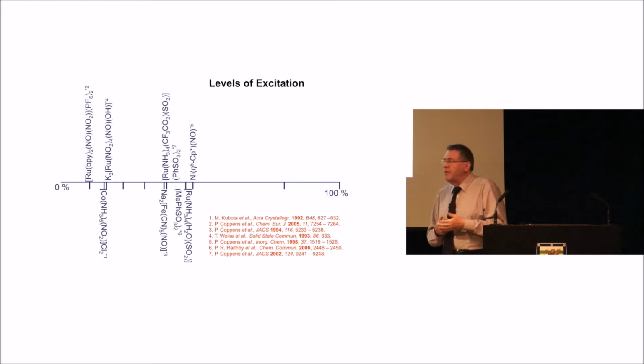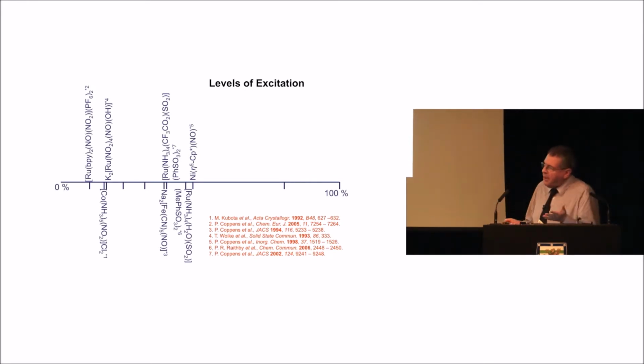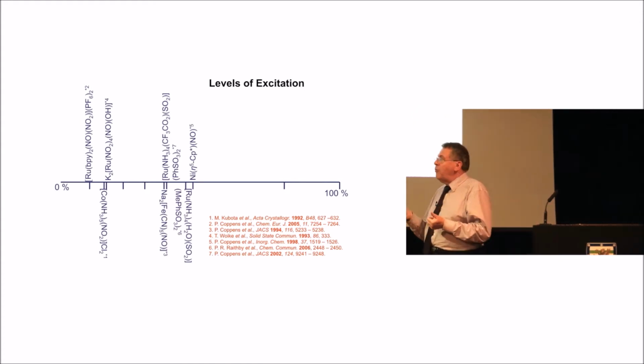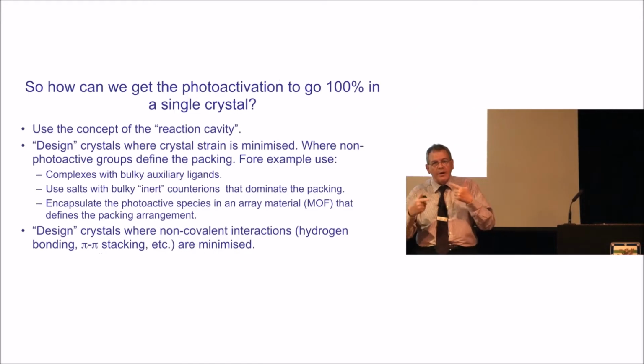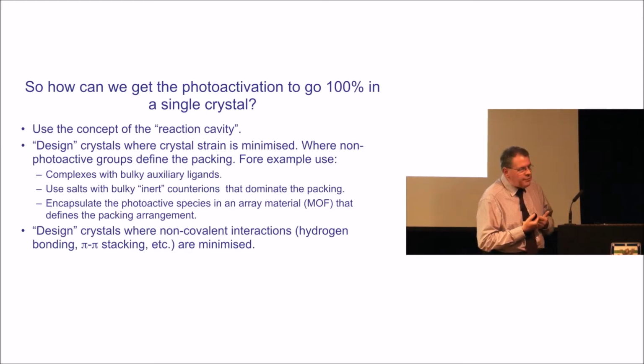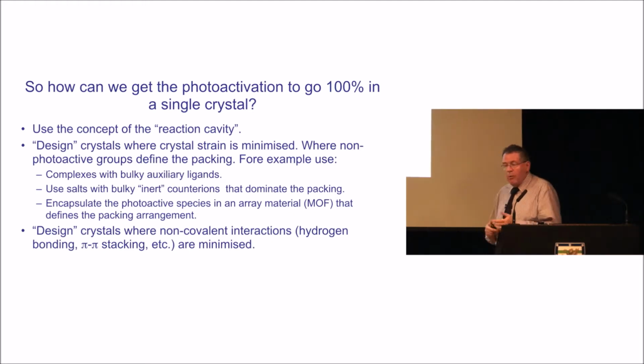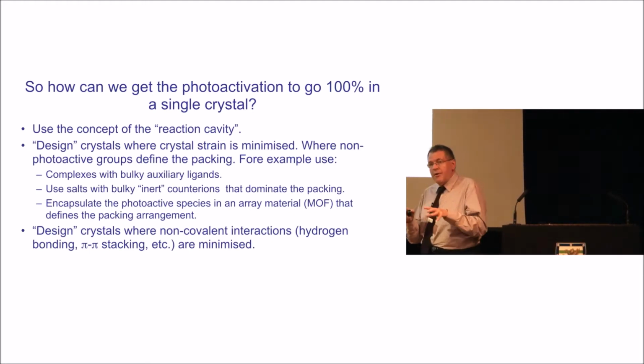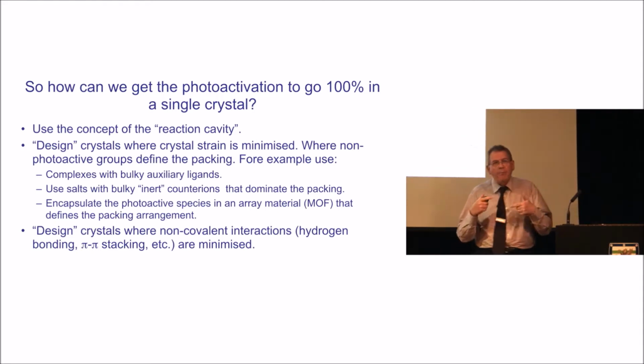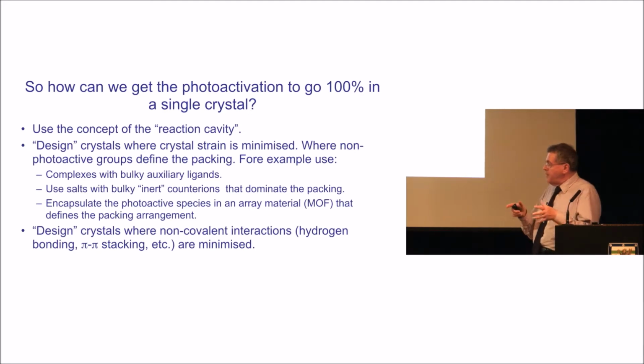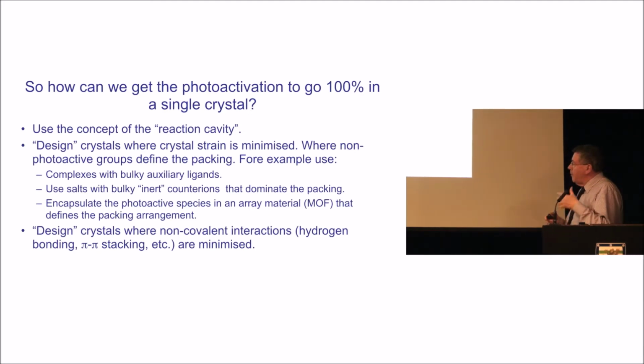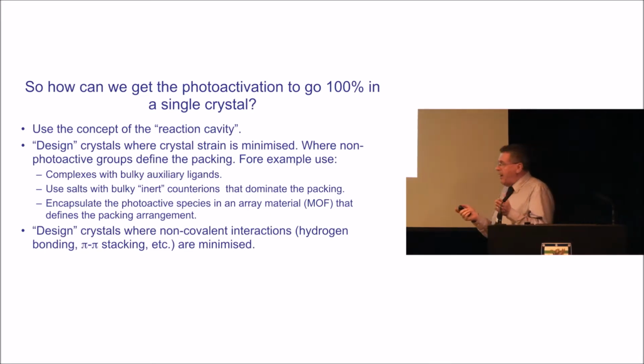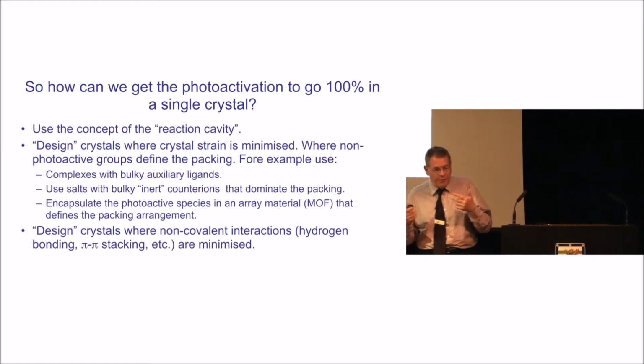All these examples showed a change in cell volume, normally an increase of less than 2%. Is this telling you something about the packing? Is this telling you something about crystal strain? How might we do this? Well, we can use the idea of the reaction cavity to give you space for this to happen. And we can do it in a number of ways. You can use bulky ligands that define the crystal packing, generate the cavity. You can use salts, which have bulky inert ligands, groups that actually define the packing that give you space, or indeed you can encapsulate your photoactive species in some sort of framework.